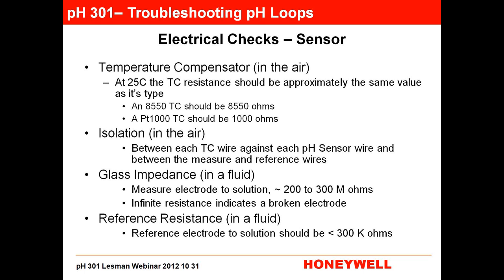To test isolation, to see if you're getting a short between some of the wires in there, like if you maybe have a crack in the glass inside the sensor and you just can't see it, but it's not behaving right, you can check between each TC wire against each pH sensor wire. So you take TC wire 1, check it against the measuring electrode wire, then check it against the reference electrode wire, and then TC 2, and check the two wires as well. You should have no conductance at all. You should have complete isolation between those wires. And when you're doing these checks, of course, the sensor is disconnected from the instrument.